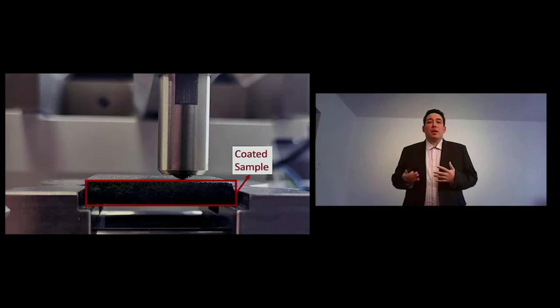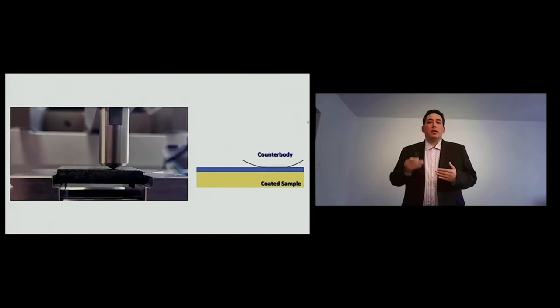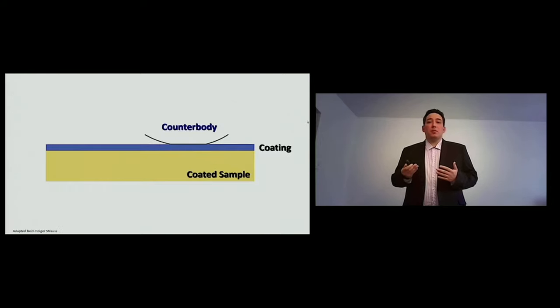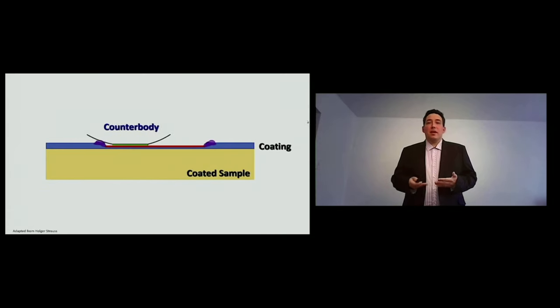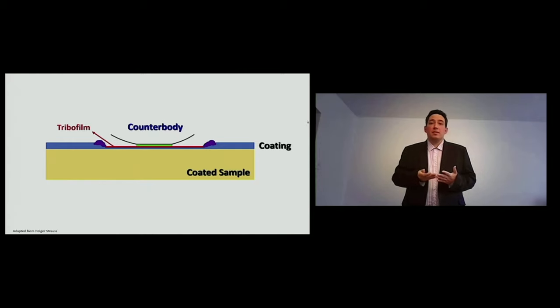So if we were to draw schematics for that, this is what you'd see. The coated sample, the coating that you cannot see right now in the image because it's too thin, and the counterbody or counterface. Well, now, if you put that into motion, what we'd see is that different things can happen at the surface. Material can get mixed and oxidized and form what we call a tribofilm. Material can also get detached from the surface and attached to the counterbody or counterface, forming what we call a transfer film. And material can leave the wear zone, which we call wear debris.